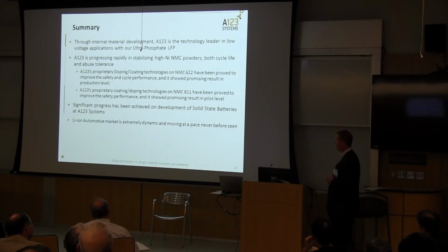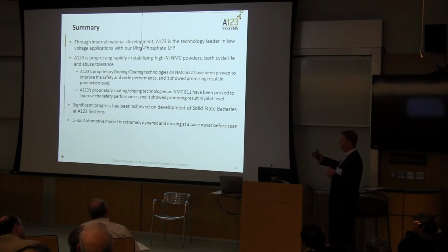We think solid-state batteries are the future, and it's key to getting to higher energy densities. We're of the same opinion that it's probably 2028, 2030 for lithium metal for solid states, but if we can get to between 300 and 350 with a graphite silicon and 80 or 85% nickel, there's value there. There's a market for that as well, and we think we can break into that about 3 or 4 years earlier when compared to lithium metal.